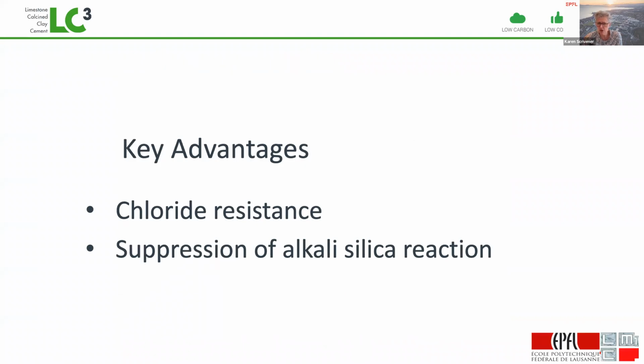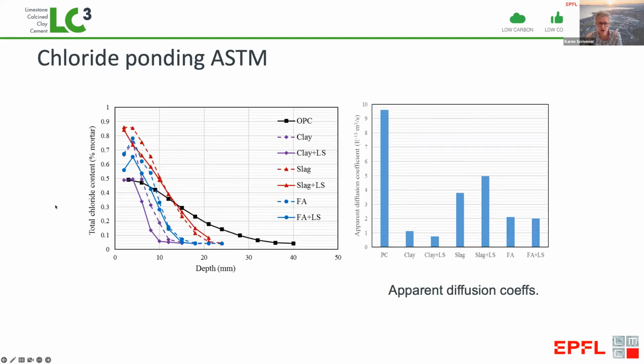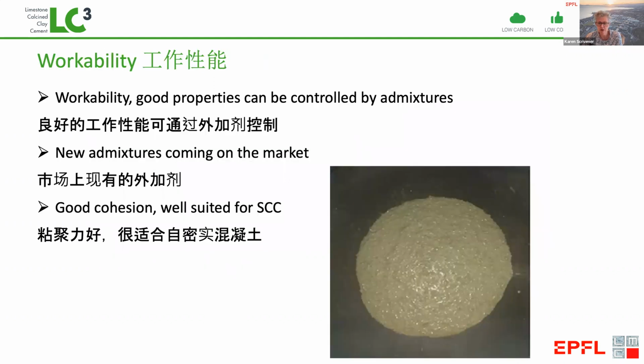Just to touch on some of the key advantages, particularly chloride resistance, which is the number one issue of durability of concrete. Here you can see the chloride penetration in the reference Portland cement. It's somewhat better with slag and better again with fly ash, but very best of all is the calcined clay limestone combination, which has an apparent diffusion coefficient which is 10 times less than the reference.